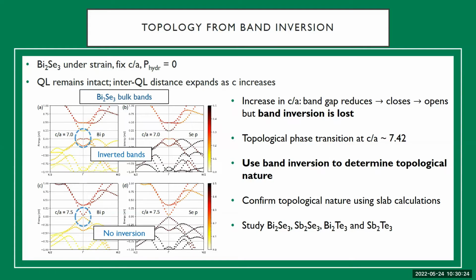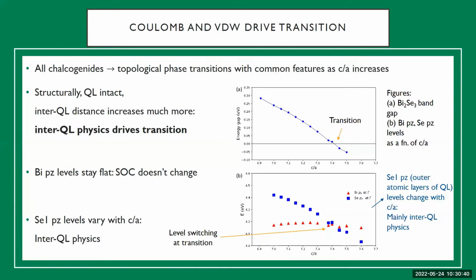And this is what, so we carried out this investigation for the whole family of materials: bismuth selenide, antimony selenide, bismuth telluride, and antimony telluride. And what we found was that all of them show this similar topological phase transition as the C/A ratio is increased. And the important thing that we found was that it was the physics between the quintuple layers which seemed to be driving the transition mostly, as opposed to the physics of what was happening within the quintuple layers.